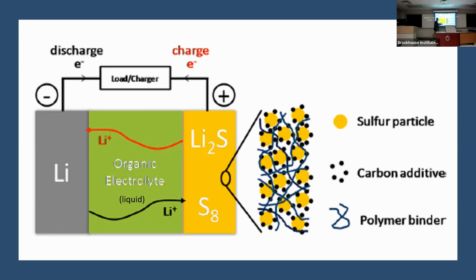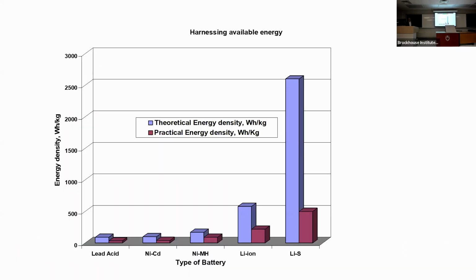Okay, and then you can see there's a sulfur particle and there's a carbon additive for conduction, and there's a polymer binder to hold them together. It's very similar to the lithium cobalt oxide and other oxide electrodes used in lithium-ion batteries. Okay. Yeah, but what stands out, you can see, is that lithium-sulfur battery has this massive energy density available. All we need at the moment is to look for 25% of the energy, reversibly available, stable, and safe. It will be much better than lithium-ion battery. So already lithium-sulfur batteries look so promising in this direction.